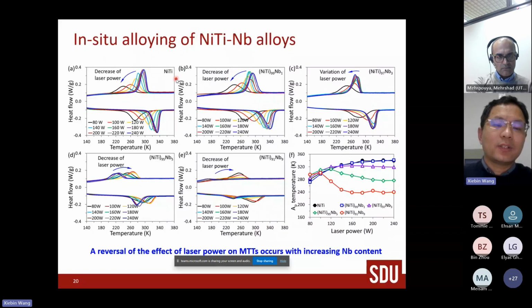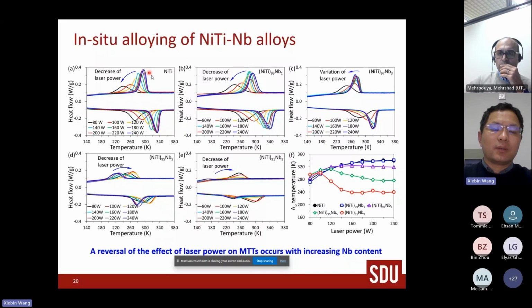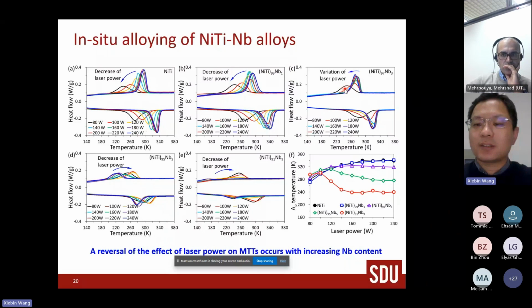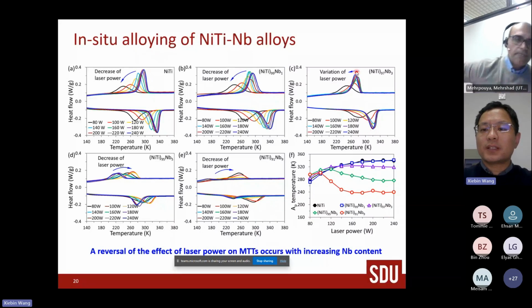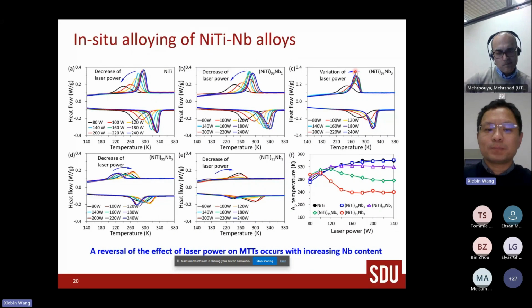We know that for the binary alloys, if you increase the energy input, you will increase the transformation temperature. For example, here, if you increase the laser power, the transformation temperature will increase from the black curve to the blue curve. And of course, if you add only 1% niobium, it shows similar trends as binary alloys. But if you add 3% niobium, except for the sample printed with very low energy density, the blue curve and the red curve, the rest of the samples show very similar transformation temperatures. So it means the transformation behavior is not that sensitive to the laser power change.